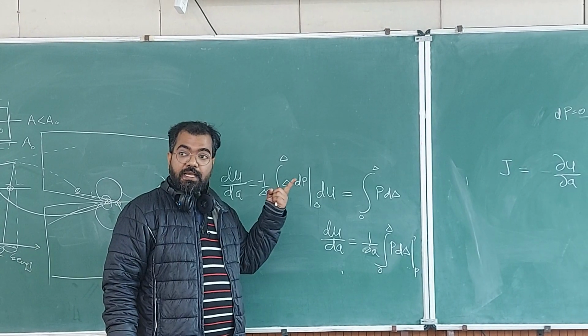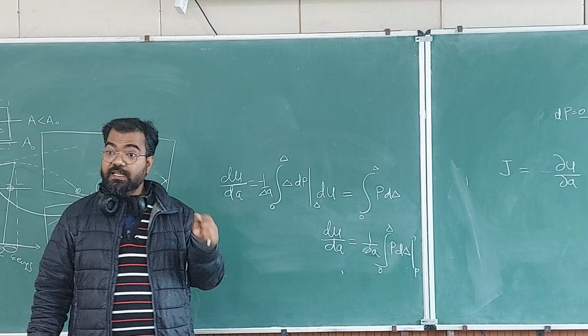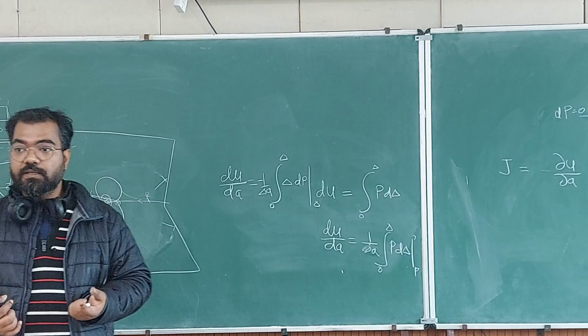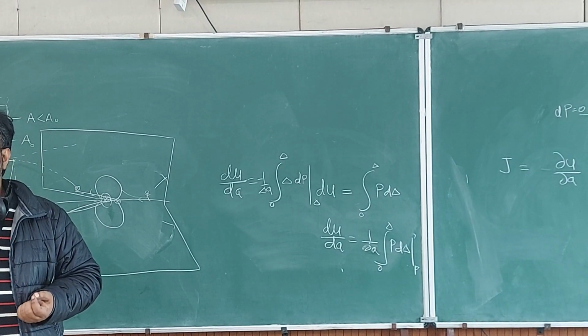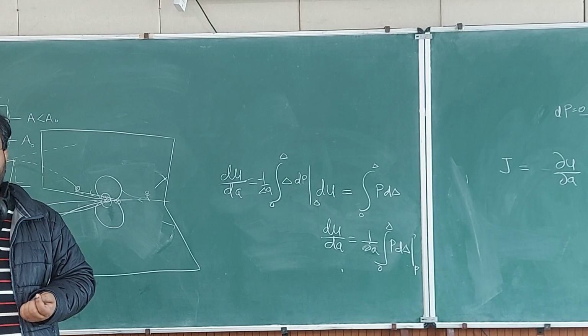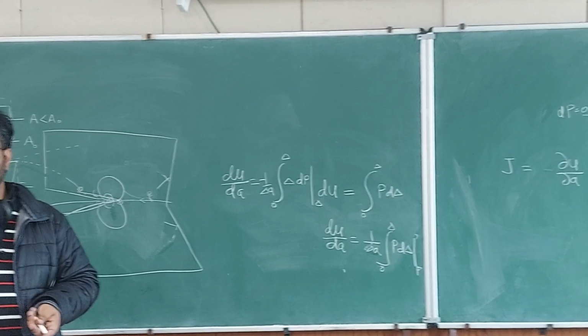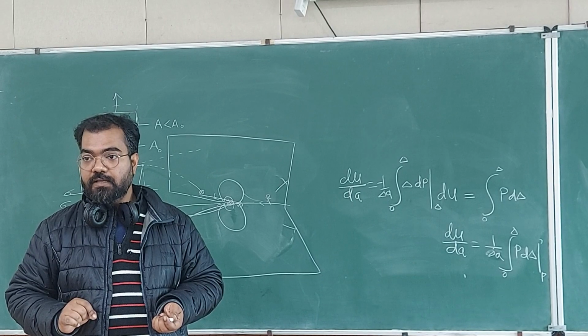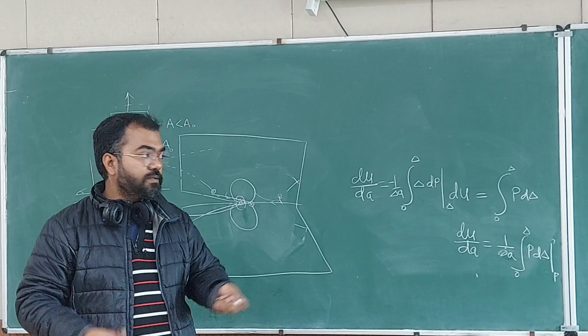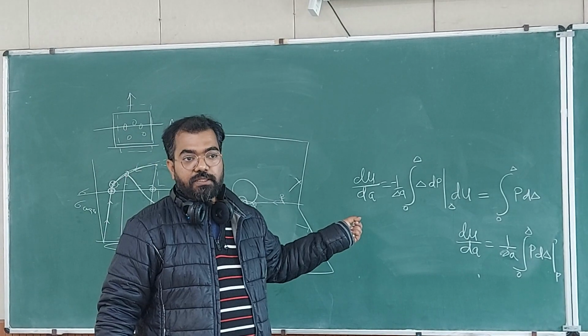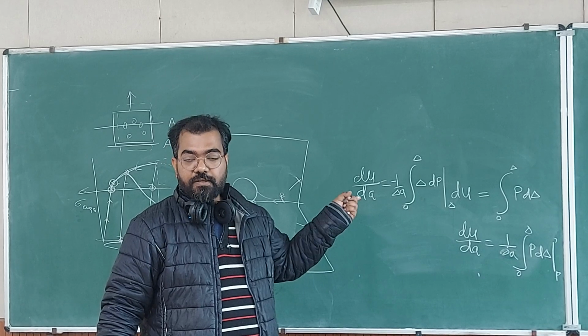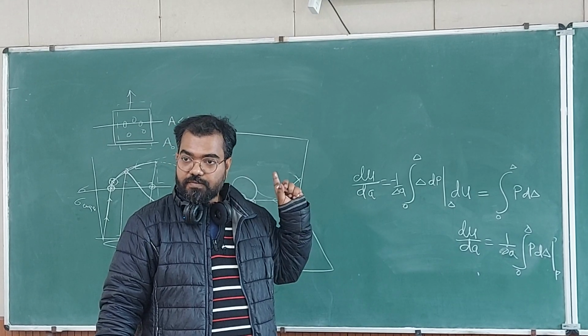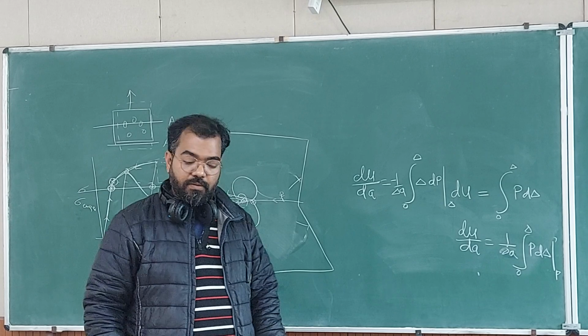The line integral equation cannot be used for measuring the integral, because you will be doing a test, and how will you measure the stresses and strains at different points on a line integral? How will you do it? Right? So you need another formulation, which is this one, to use it for the measurement when doing an experiment, similar to Griffith. Okay?